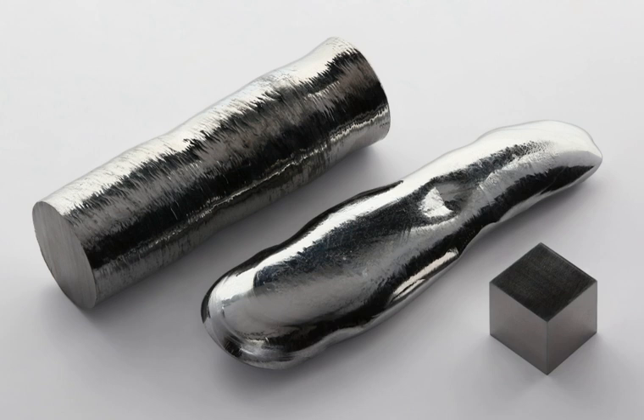c = 445.6 pm. Its usual commercial form is a powder, but this element can be consolidated by pressing and sintering in a vacuum or hydrogen atmosphere. This procedure yields a compact solid having a density above 90% of the density of the metal. When annealed, this metal is very ductile and can be bent, coiled, or rolled.